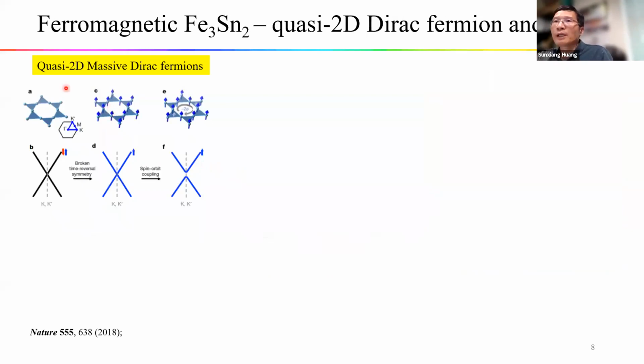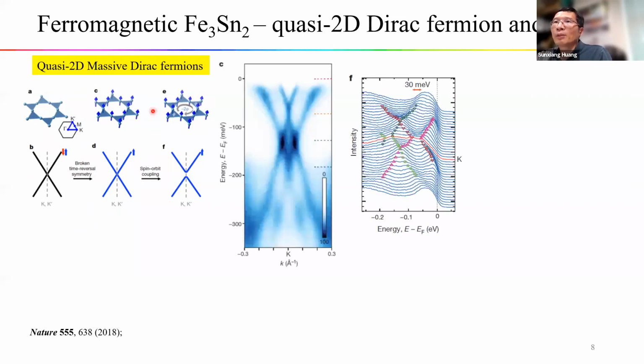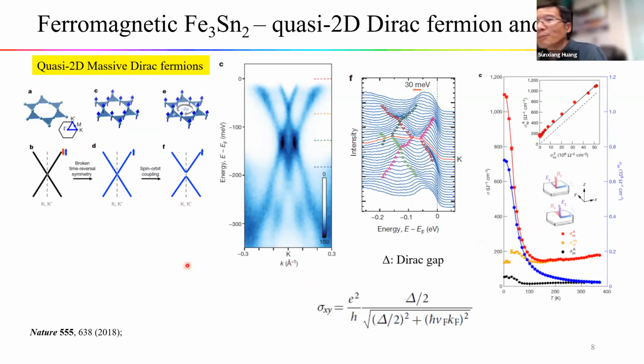As mentioned, this Kagome lattice gives rise to massless Dirac fermions. If the time reversal symmetry is broken by this ferromagnetism, the spin degenerate Dirac bands are lifted. Inclusion of the spin orbit coupling opens the Dirac gap. So this is the idea about the band structure. Experimentally, the photoemission measurement indeed observed this Dirac gap, about 30 meV, at about 70 meV below the Fermi energy. In this paper, they suggest the large anomalous Hall observed in these materials arises from this massive Dirac gap.